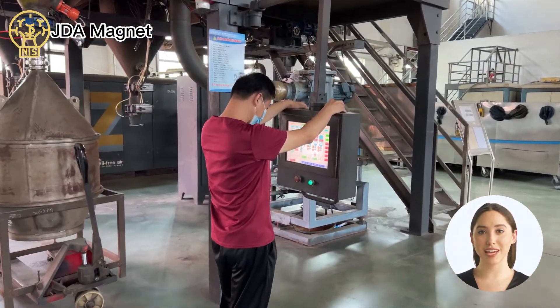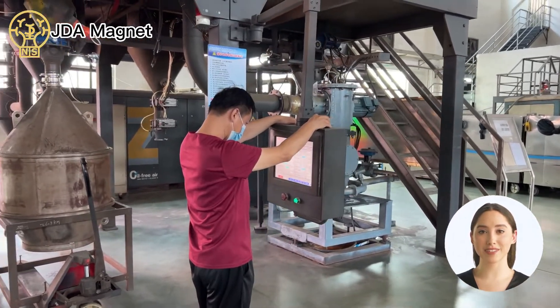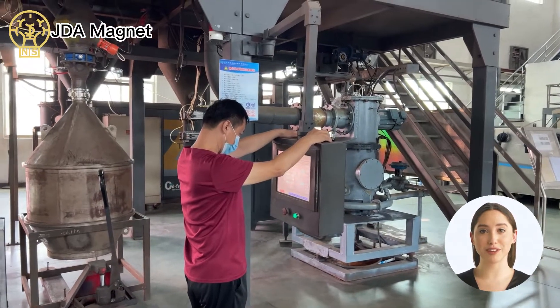For the preparation of Nd-Fe-B magnets, the powder size should be 0.7–7 μm; that is, the average particle size is in the range of 3–4 μm.